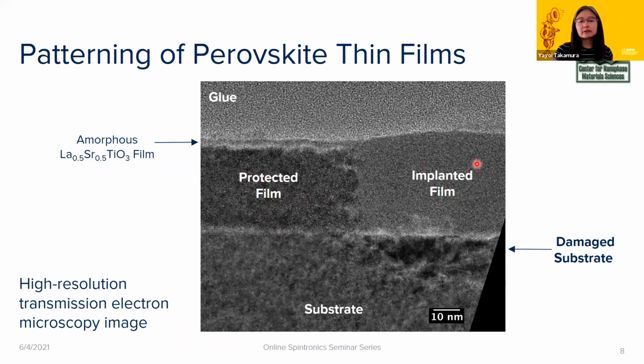The implanted film is amorphous, right? And then here's the substrate, and we see that some of the damage does go down into the substrate as well, but we can have a fairly sharp, though not atomically sharp, interface between the protected and the unprotected regions. So again, we get these magnetic islands embedded within this non-magnetic matrix.